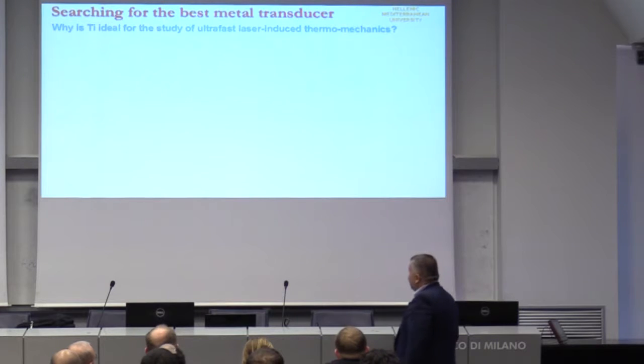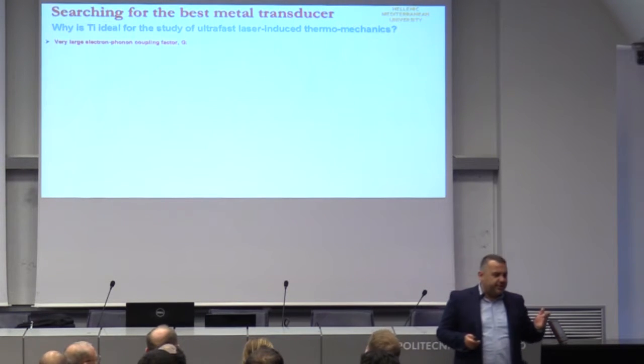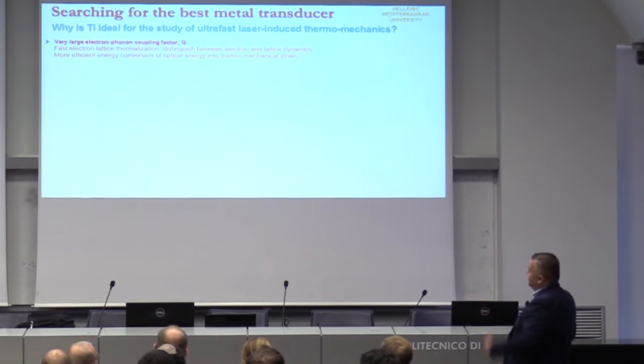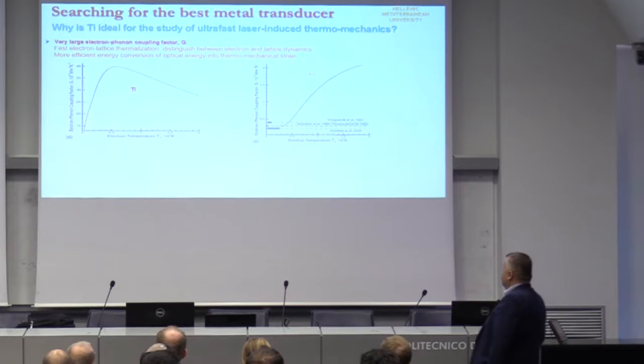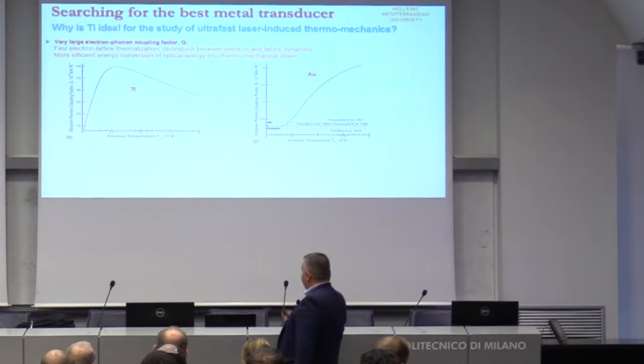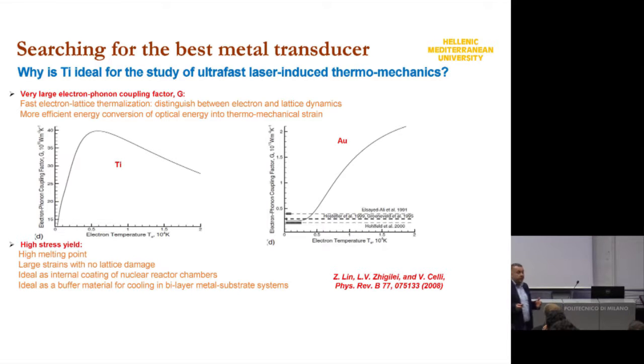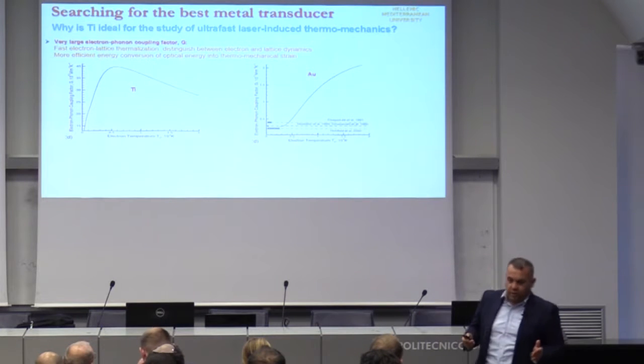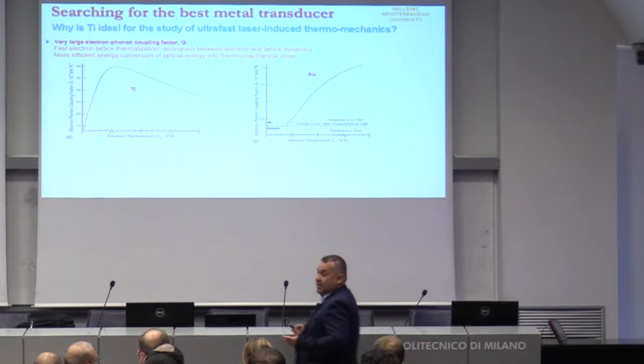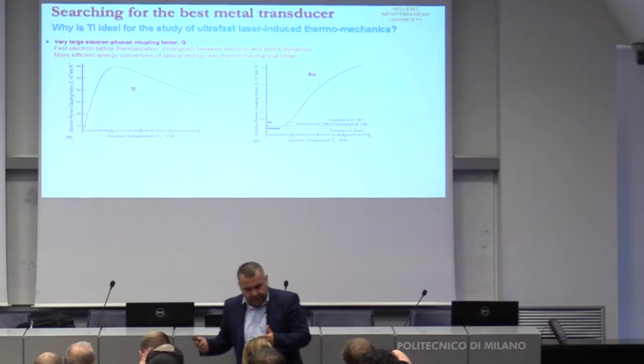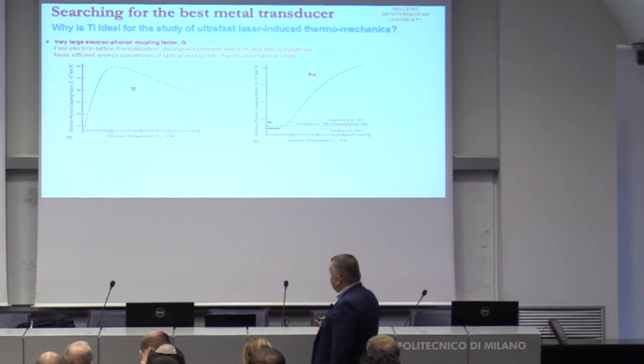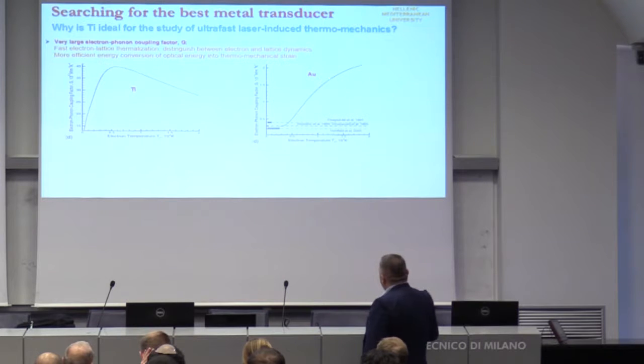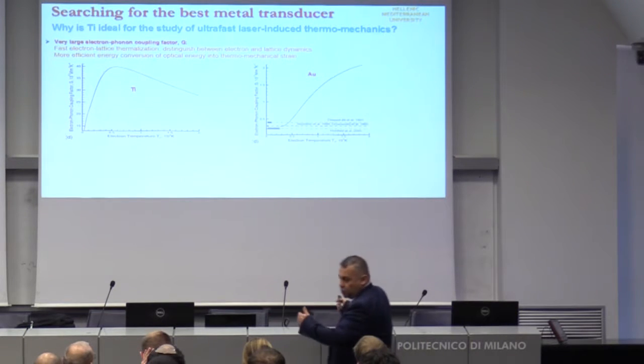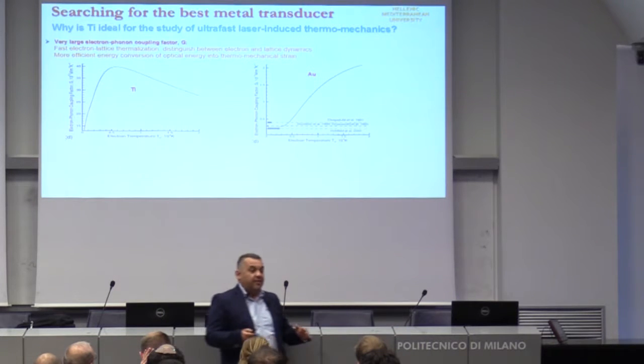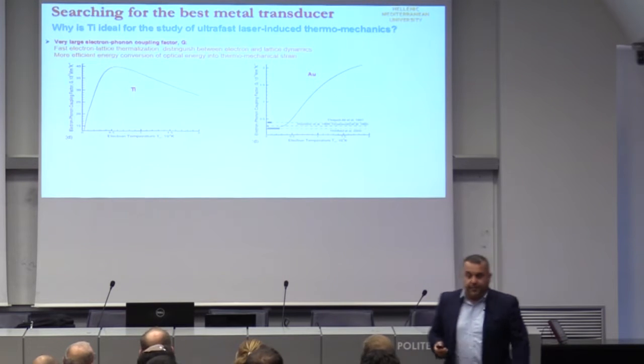Now, the first thing in research, for example, is searching for the best transducing material. Let's see, for instance, two metals, titanium and gold. For titanium, there is a very important parameter for this kind of transducing, which is the electron-phonon coupling factor, the G factor as we call it, which is actually how fast the energy of the electrons is transferred to the lattice vibration. And if you see here, titanium from a certain temperature is, for example, 40 times 10^17, whereas gold never reaches in this area more than 1 or 2 times 10^17. So titanium is a material which has a very high electron-phonon coupling factor.